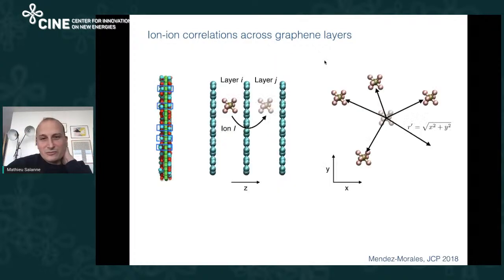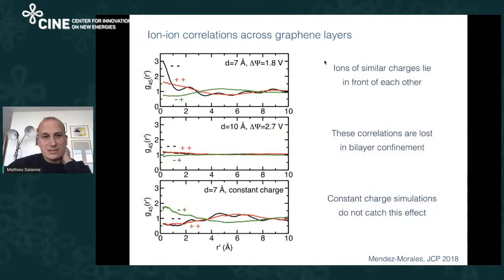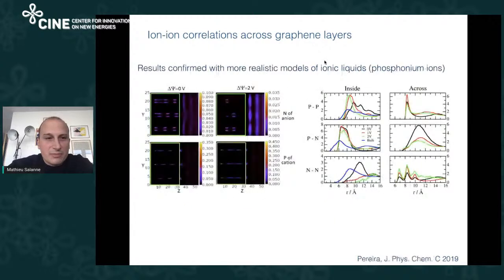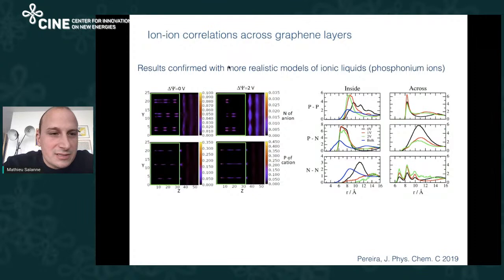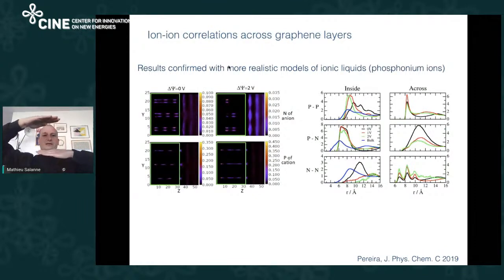And in fact, we characterized this further, and you can see that this is a very strong effect. Maybe I will not show it on this picture, but maybe on this one it's better. You can see here on these maps, on the top, you have some maps of anions, and at the bottom, you have maps of cations. And you really see that the anions stack one in front of each other, and cations do the same, but not in the same position.